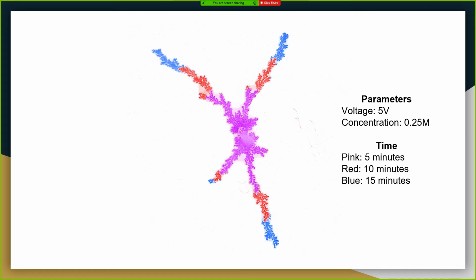I know in the Santos and Santos paper, they reported on this happening. The other thing I could think of is it's a combination of things where, depending on what voltage and concentration you're growing the clusters at, you can expect a certain amount of branches. When you're at low concentrations, you usually get fewer branches, and when you get higher, you get more branches. So it could be that playing a role in the fact that on the right-hand side there, you're not getting much growth, but they don't get into specifics other than what they think it could be. So yeah, I agree, I don't think that necessarily either of those would answer the question unless the electric fields are playing a much bigger role.